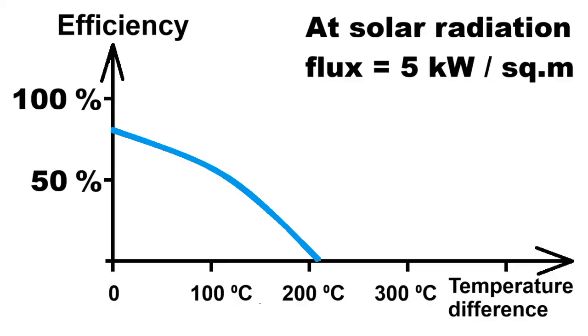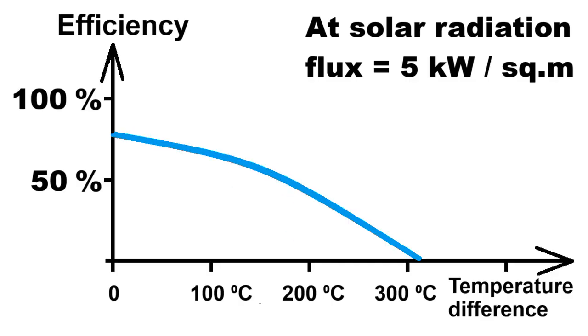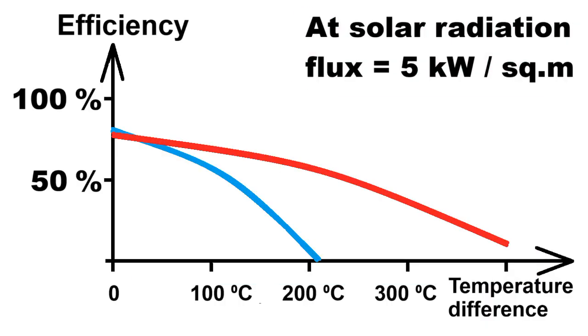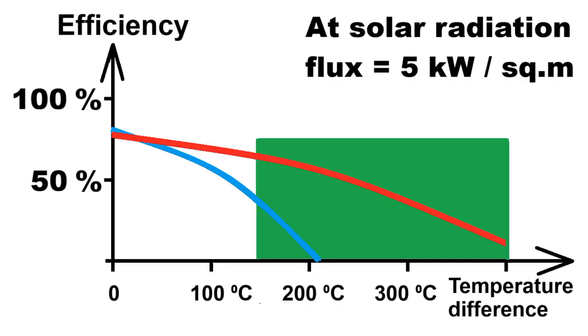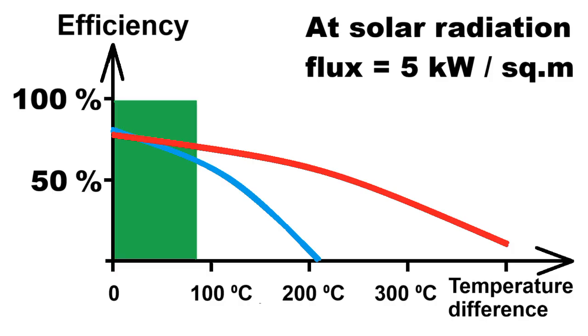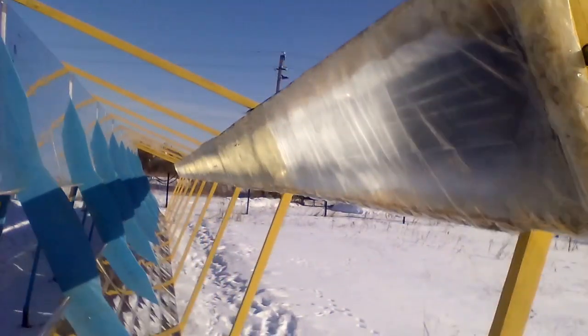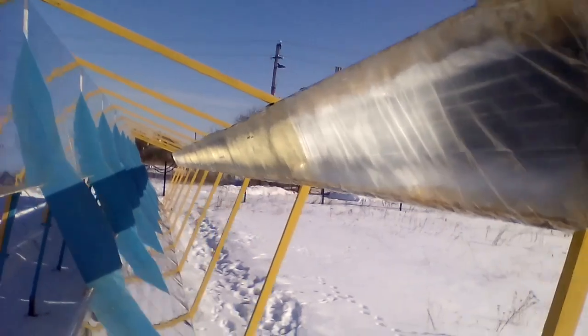This is the percentage of efficiency of my receiver, and we see that the percentage decreases due to the increase in this temperature difference between the heat transfer fluid and the surrounding air. If it is not black paint but a selective coating, the efficiency will improve approximately like this. The efficiency of these evacuated tubes will be like this at this flow of concentrated solar radiation. We see that an evacuated tube will be radically better at these high temperatures, but my receiver is more suitable for these low temperatures, which are needed for heating pool water and home heating. In addition, this large height of the receiver is an advantage if we use cheap mirrors of poor accuracy, or for other reasons which will be described in the next video.